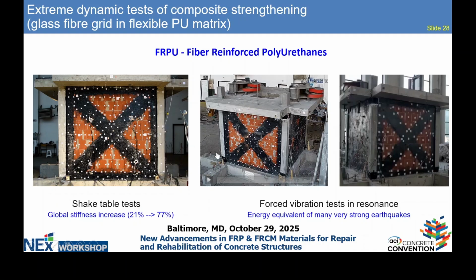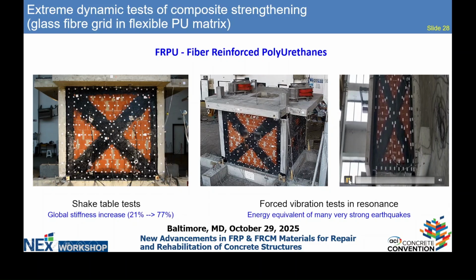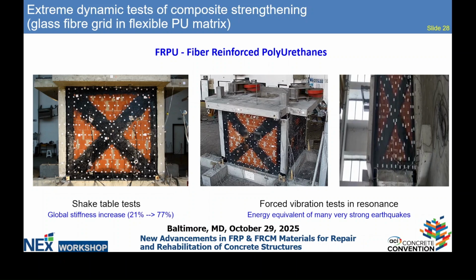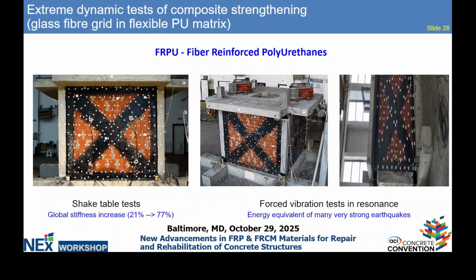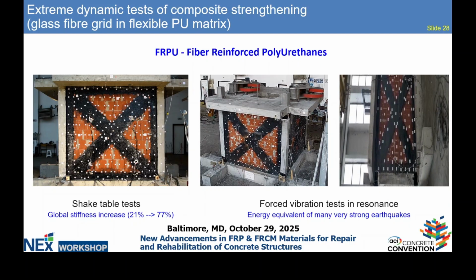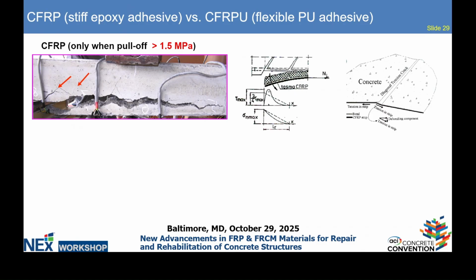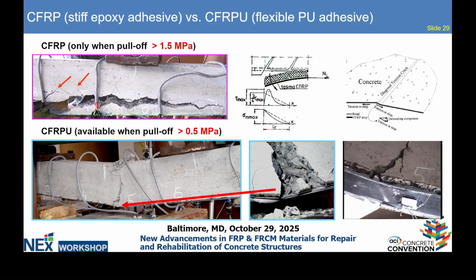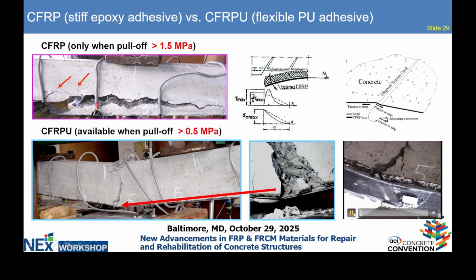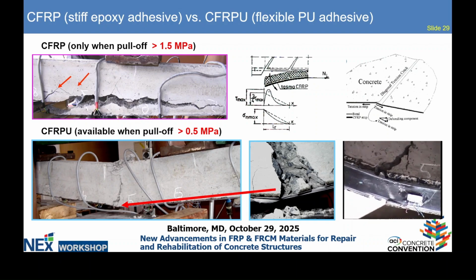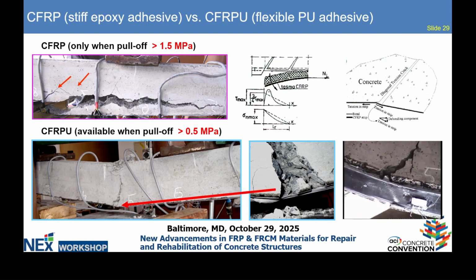So now I would like to show the movie. This is forced vibration test resonance, so equivalent of many strong earthquakes, and the structure survives. I apologize for this quality of the movie. So now when we are using composite materials as strengthening, I mean FRP, in this sense we have stress concentration that causes delamination. When you use CFRPU system, I mean the flexible polyurethane as an adhesive, in this sense you are able to transfer high loads and high deformation simultaneously, but also to protect structure against collapse.